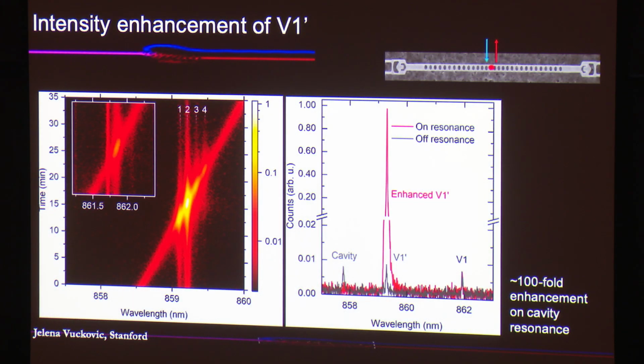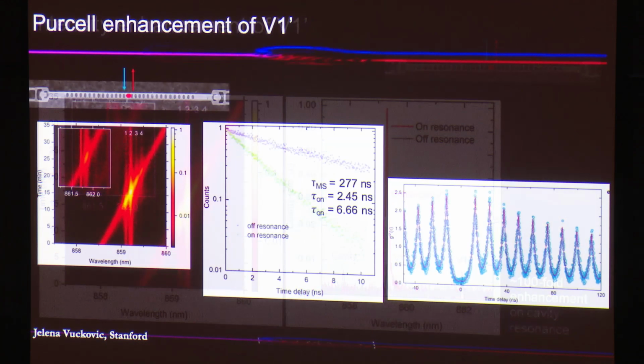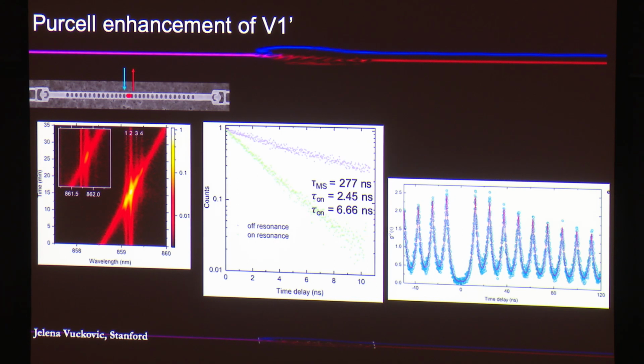But also quantum emitters are really good. And they're not degraded relative to the wafer. So when you embed them in these silicon carbide structures, these silicon vacancies are there. They're enhanced when you couple them to cavities. You see 100-fold enhancement on cavity resonance. As you tune your cavity onto the emitter, it just lights up. You also see a reduction in radiative lifetime, what we call Purcell enhancement. And this is all for a single quantum emitter, which is proven from the photon statistics measurements.